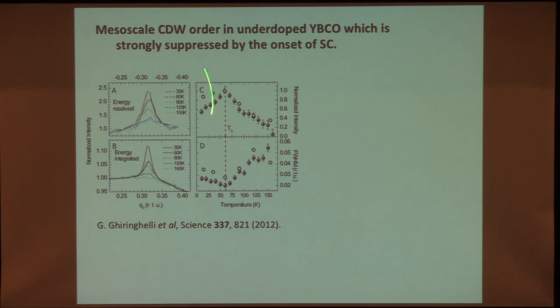You do it with the same device that you do resonant inelastic. And you see there's this nice charge ordering peak. It starts growing as you lower the temperature. Interestingly, then it reaches a maximum and starts decreasing. Here's the peak height as a function of temperature.